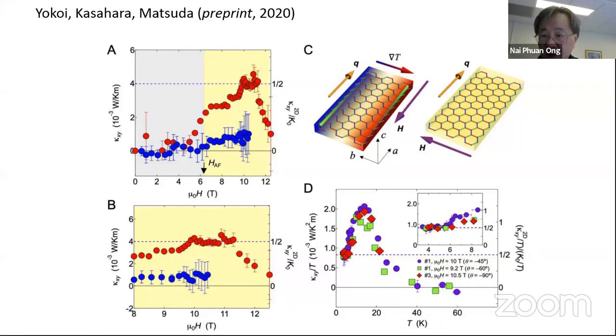So this is an anomalous thermal Hall effect, right? Obviously the Lorentz force is not involved here, and there should be no Hall signal. But when it appears, it again appears within the thermal Hall quantum spin liquid regime, and it approaches quantization, but now with more scatter. Again, there are no data below 4 Kelvin that we could see. Let's say, for example, here, right? It goes down to maybe 3.6, 3.7 and stops there. And what we did then was to extend the measurements down to 0.3 Kelvin, 0.35. So a factor of 10, right? And try to sort of match up to that data.